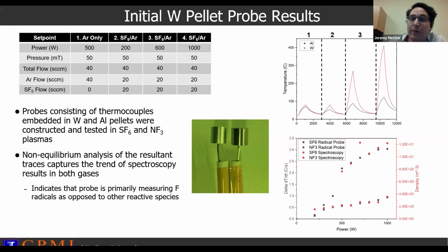pretty consistent etch results. When we compare them in both SF6 and NF3 to the densities as measured by spectroscopy, we can see that the probe seems to capture well the increased density that we would expect to see in an NF3 plasma as compared to an SF6 plasma. So this was really encouraging, that we're able to measure not just some side radical of SF6, SF5, SF4, et cetera, but actually the fluorine itself, because we're getting response in not only an SF6 plasma but in an NF3 plasma, like what we would expect according to the density measured by spectroscopy. And this was done using the non-equilibrium analysis.